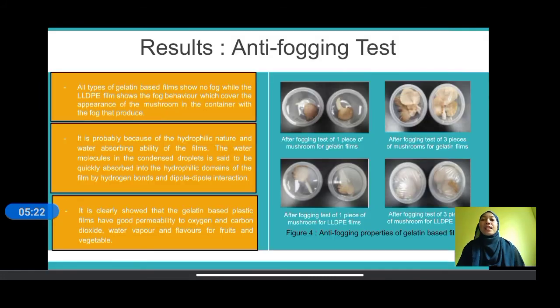Next, the result of the anti-fogging test, in which we can also say that all types of gelatin-based film that we studied, whether added with glycerol or not, show no fog, while the LLDPE film shows fog behavior, which covers the appearance of the mushroom in the container with the fog that was produced after we undergo the fogging test. It is probably because of the hydrophilic nature and water absorbing ability of the films. The water molecules in the condensed droplets are said to be quickly absorbed into the hydrophilic domains of the film by hydrogen bonds and dipole-dipole interaction.